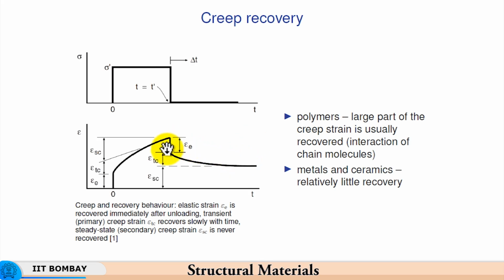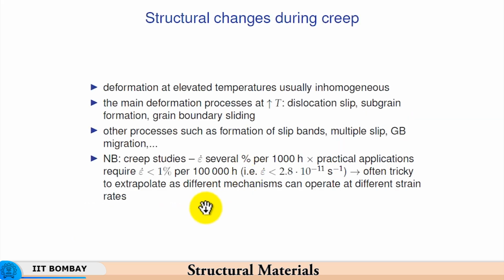So, creep is not such a major problem in the case of polymers, but for metals and ceramics the recovery is very little. This is the final creep strain at the maximum load, but when you release the load, not everything gets recovered, very little gets recovered here, and that is the reason why one needs more attention with metals and ceramics. Creep of metals and ceramics requires greater attention because the creep strain is retained to a substantial degree.